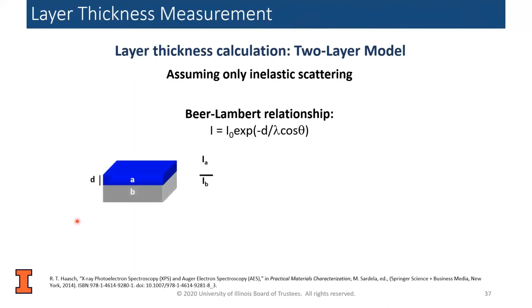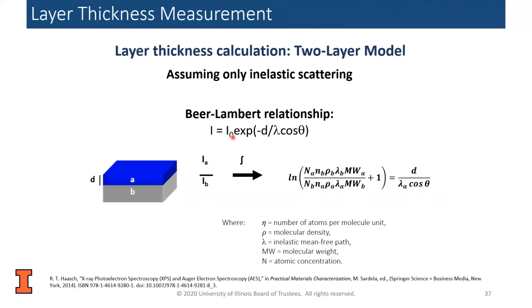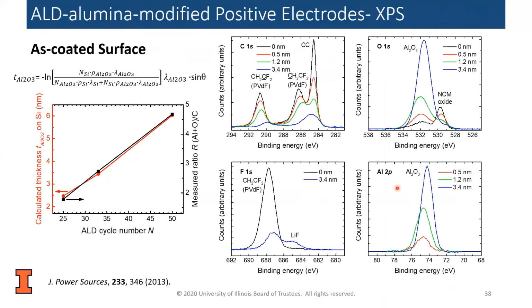So what we'll do is we'll develop a two-layer model, and then we'll form an equation for each layer, integrate, and we'll come up with an equation here that we can use the intensity to estimate a thickness. So the first thing we wanted to do in our case was determine a way to actually estimate the thickness on the electrode. As you might imagine, the surface of these electrodes is definitely not two-dimensional planar.